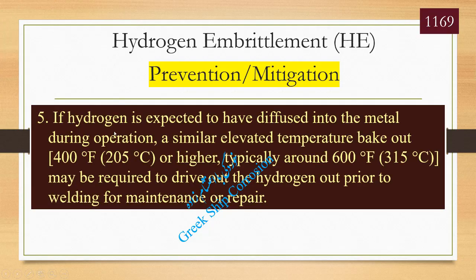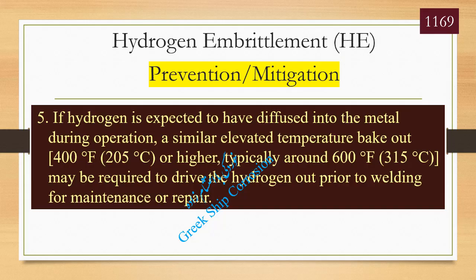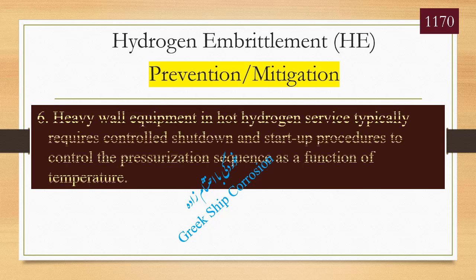5. If hydrogen is expected to have diffused into the metal during operation, a similar elevated temperature bake out, 400 degrees Fahrenheit or higher, typically around 600 degrees Fahrenheit, may be required to drive the hydrogen out prior to welding for maintenance or repair. 6. Heavy wall equipment in hot hydrogen service typically requires controlled shutdown and startup procedures to control the pressurization sequence as a function of temperature.